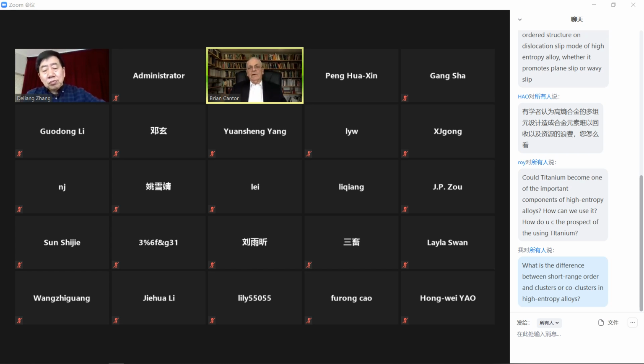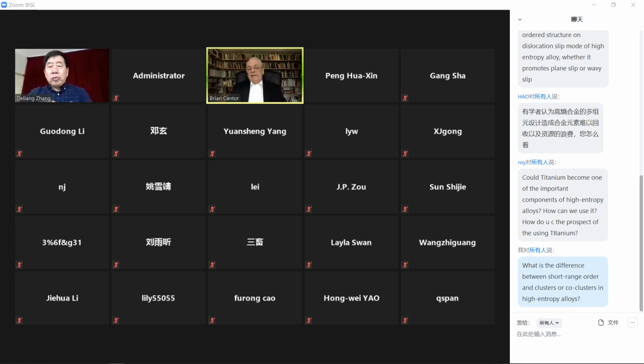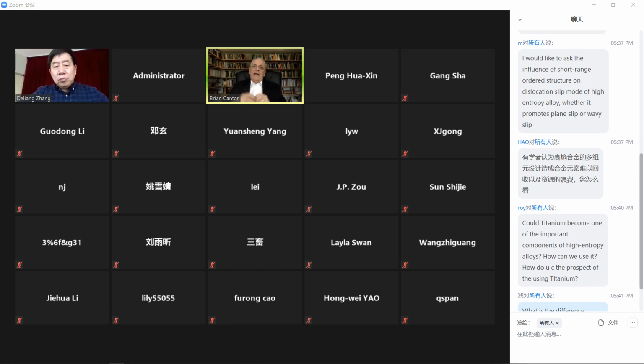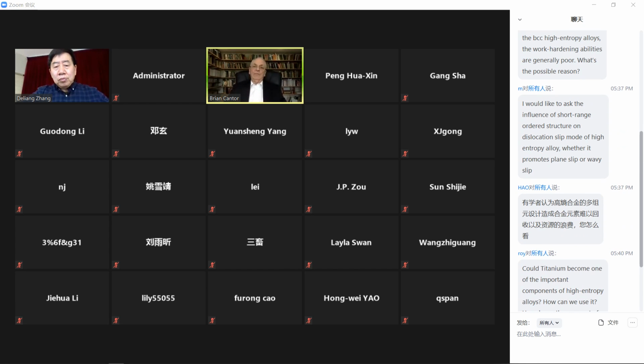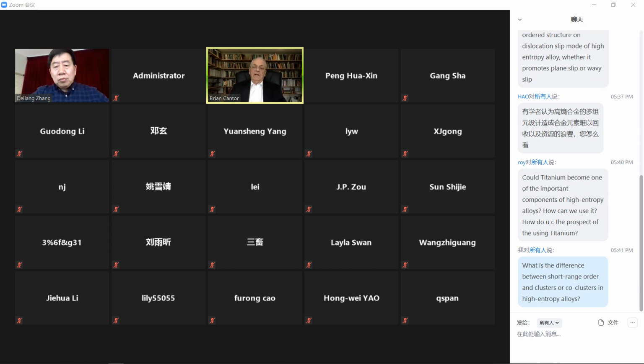Now, if you go to non-equiatomic compositions, or if you change and add in some other components and have different basic components, even equiatomic, if you say add copper and take something out, or take out the chromium and so on. If you change the composition, go to different places within the FCC region, within the Cantor alloy region, you begin to see more short-range order, and people have measured the short-range order. Obviously, if you go far enough, that short-range order begins to manifest itself by interactions between the atoms, which lead to compound formation, and you move outside the single-phase region. And that's an important region too, because then you're starting to get the precipitation hardening.